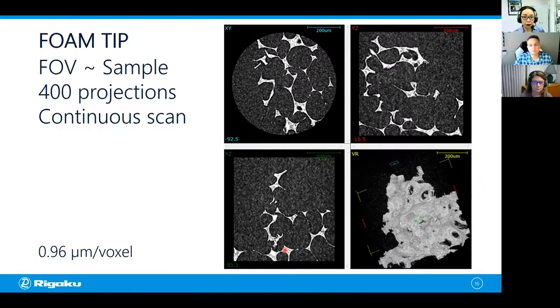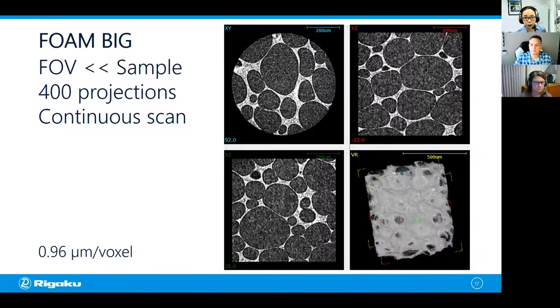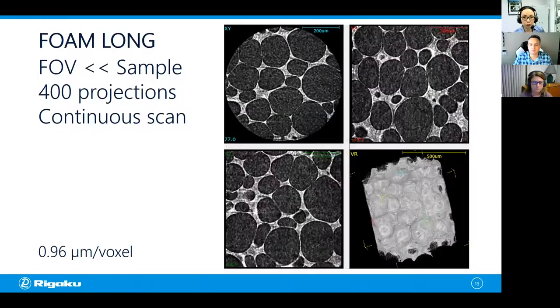So in this case, you want the sample to be a little bit bigger than the field of view so that you will scan the intact center part. Now, if you make the sample a little bit bigger, you're going to scan like this. This is bigger than the field of view, but not long, kind of a chubby sample. This one looks pretty good. I don't see any streaks and you don't see any damage from the sample sectioning. So this looks pretty good. And if you do a long one, like the one we just did, you might or might not see those streaks coming from the sample movement.